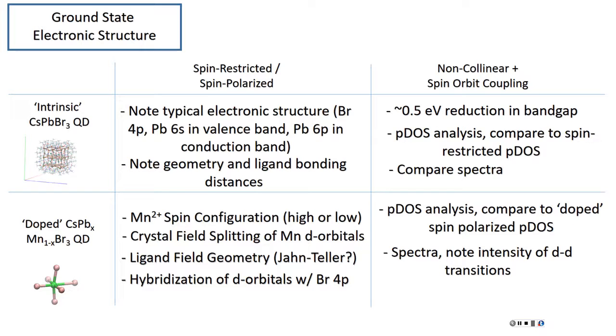It's a very common distortion when you have an octahedral structure, right? And then the bond on an apical, or whatever you call it, on the top and bottom, from like you have 4 atoms lying on a surface, right? And then top and bottom ions, they are either longer than the bonds which are for your 4 guys which are in the surface, or shorter, right? So you either squeeze it or elongate it. And then it's also known, from the simple geometrical point of view, molecular orbital theory gives you the splitting between your d levels based on this perturbation. But in your case, your perturbation is really just one bond is increased on a surface. I mean, those 4 which are laying on the surface.